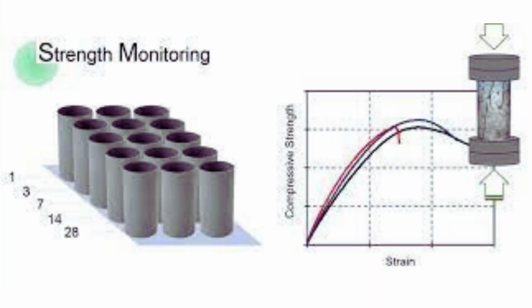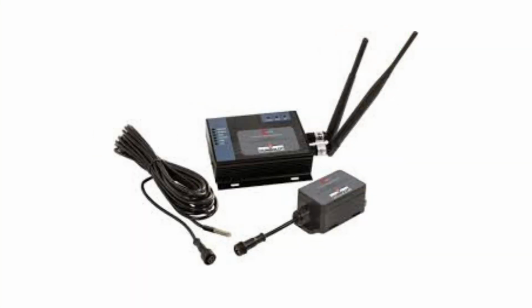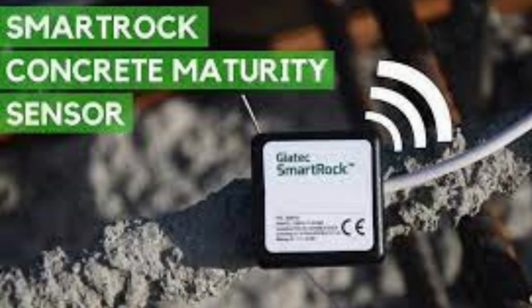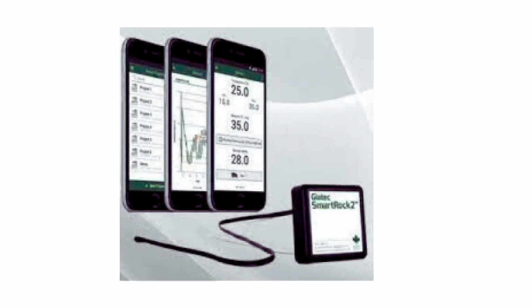Maturity testing monitors the concrete's curing process by measuring temperature and time. In this test, we can also use sensors which are placed in the beam, slab or column while concreting. These sensors are connected with Wi-Fi, so they give the temperature and time data. From that data they also give the maturity of the concrete.